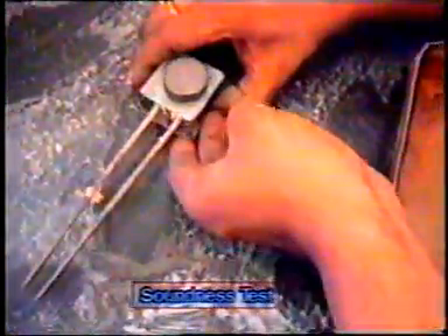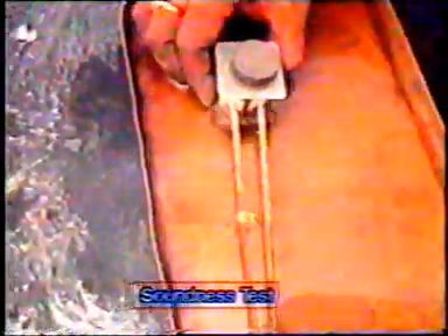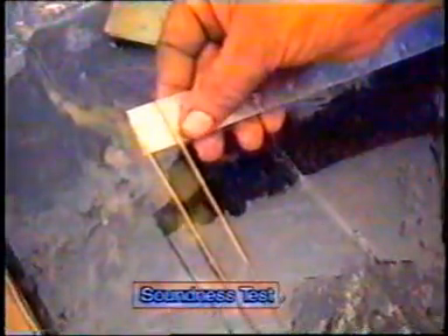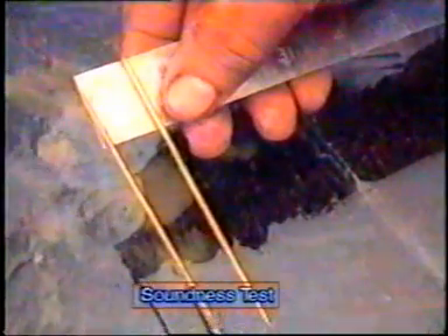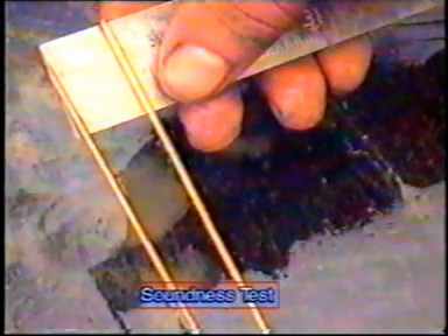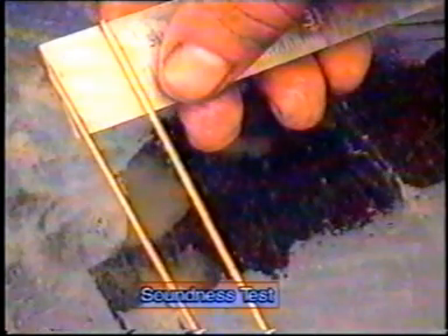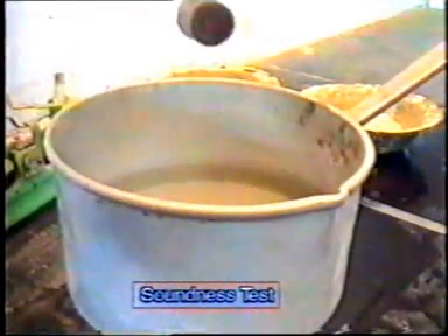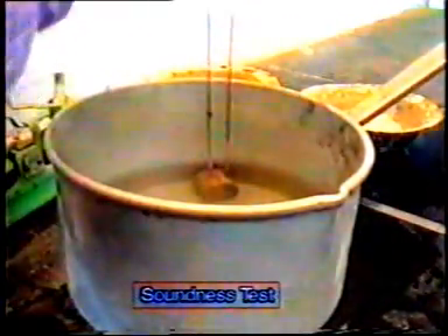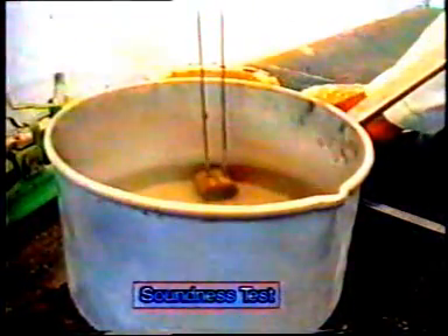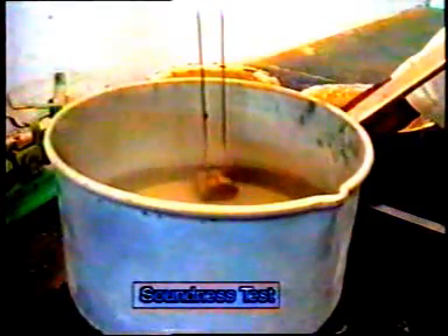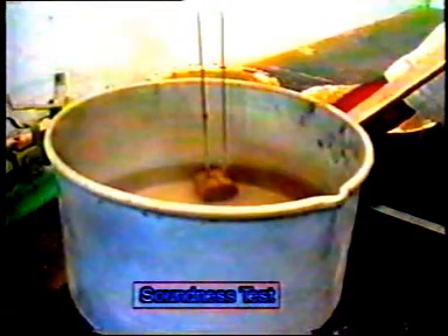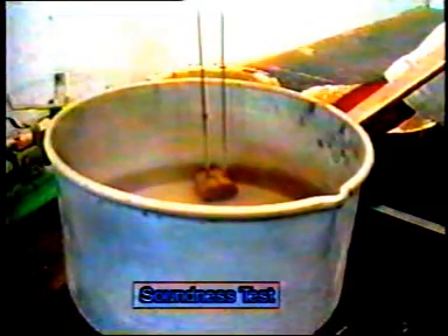Put the entire setup in the water for 24 hours. Take out this cylinder and measure the distance between the two indicators. Let it be L1. Place the cylinder again in the water and the temperature rises to boiling temperature in about 35 minutes, and allow it to boil for 3 hours.